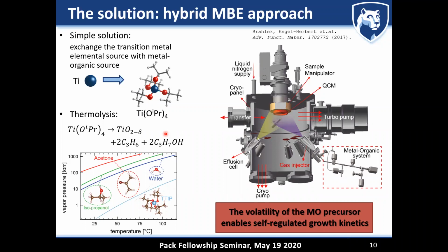Okay. Well, where does the PR go, or what happens to that? That element, PR. Oh, where does it go? Okay, so this is the abbreviation for propoxy. So basically, titanium here in this case is coordinated tetrahedrally by oxygen, and that oxygen is actually part of a propoxy group. See, there's C3. This is the propoxide, the alcohol C3H7OH. You basically take the hydrogen away, and you mount one bond to titanium, and you do this 4 times. And that's literally what people do here. It's very straightforward. Since the 1950s, people know how to do these metal organic precursors. This particular one is called an alkoxide because you're mounting an alkoxy group, in this case the propoxy, to the titanium.